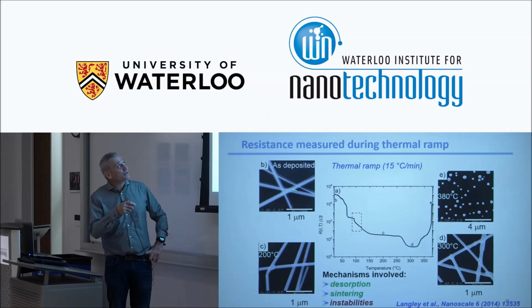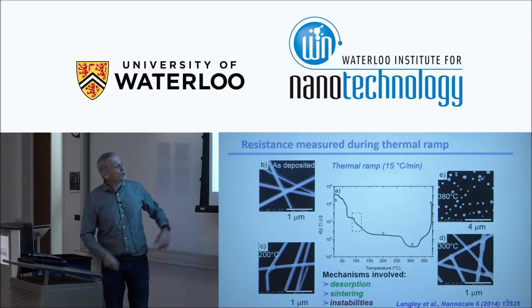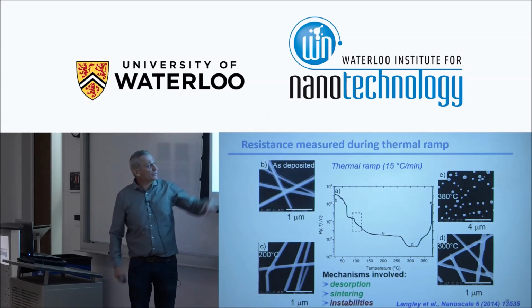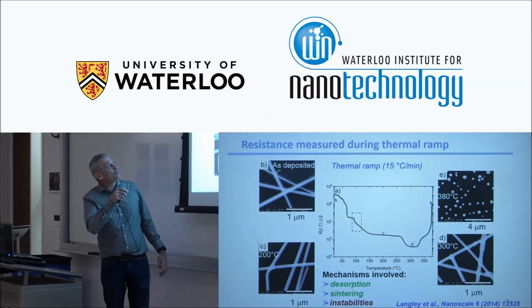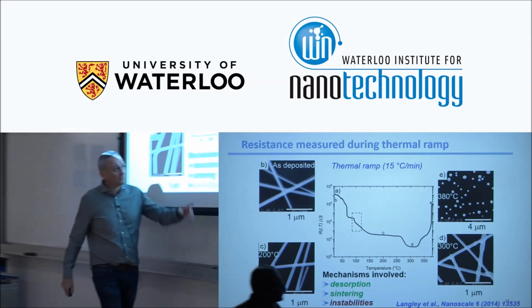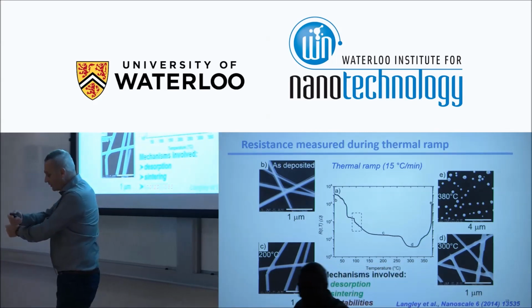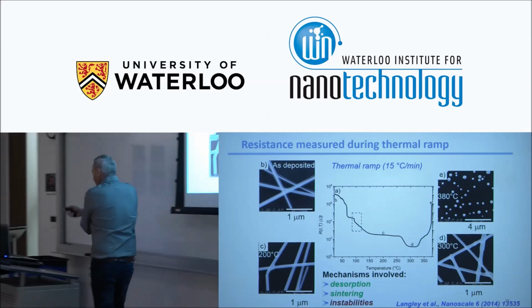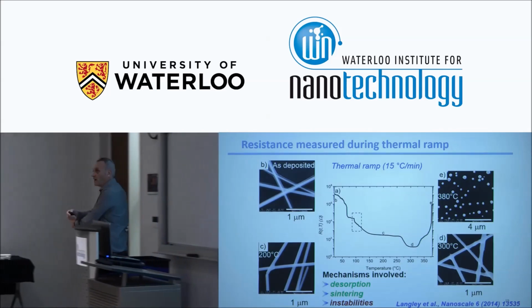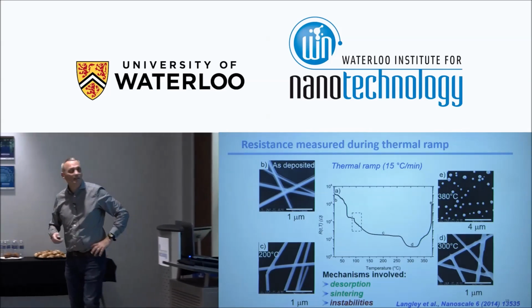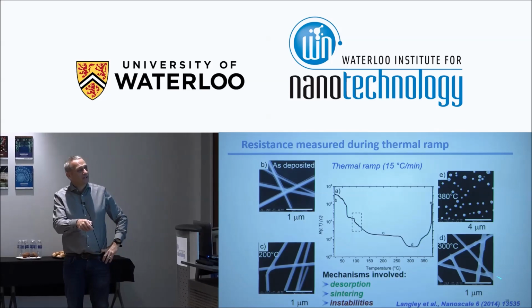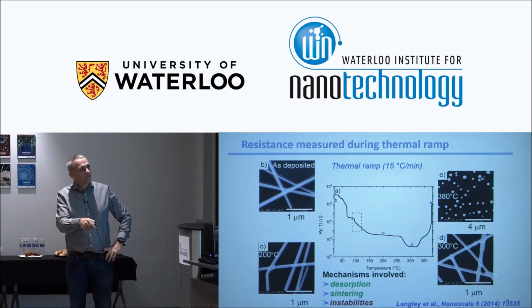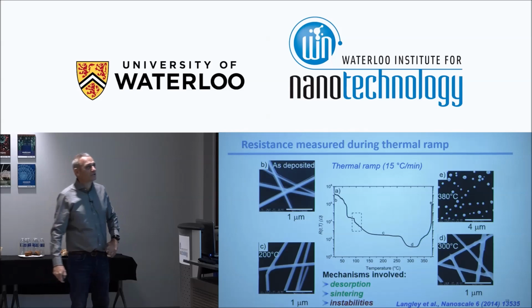This is the SEM picture just after deposition. When we anneal for 10 minutes at 200 degrees, we can see the organic residue around has dissolved. And then we have a local sintering at the junction between nanowires. There's a nice sintering, because when we deposit nanowires, often the contact is rather small, so the junction resistances are high. And if we perform an annealing, for example here 10 minutes at 300 degrees, you can see there's a nice local sintering, and that helps to decrease the junction resistance.